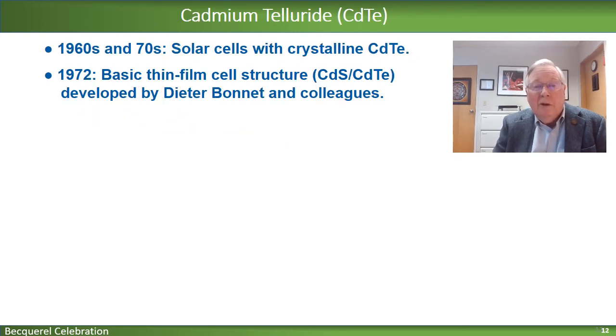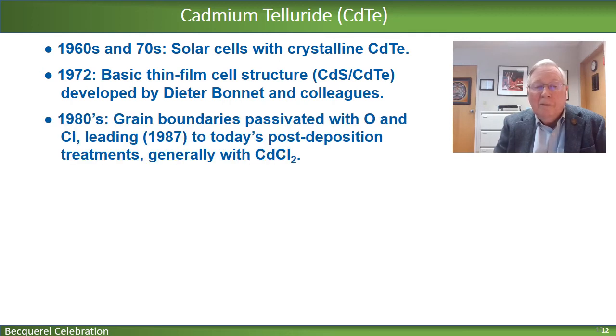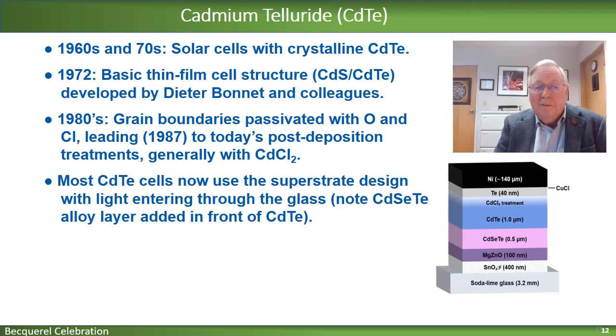Now turning to cadmium telluride, it also started early on with crystalline solar cells, and in 1972, the basic thin film structure, which is to say N-type cadmium sulfide, P-type cadmium telluride, was developed by Dieter Bonnet and his colleagues in Germany. In the 1980s, a fairly important thing happened. These grain boundaries, which I've mentioned, were passivated, which is to say the defects were toned way down with oxygen and even more so with chlorine. And that led in 1987 to what today is widely used as a post-deposition treatment.